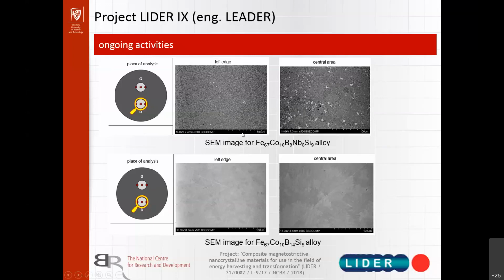But if we compare the top images with the bottom images, we can see that in the bottom images the structure is barely seen. So it tells us that it might be an amorphous material. And we can see that in the central area there are some differences between the colors, so there might also be different phases of material.